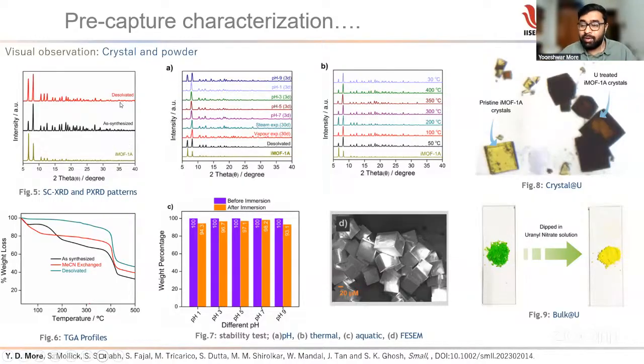So after doing the basic crystallography of the MOF, what we did, the desolvated, that is activated phase of the MOF, was treated in different acidic and alkaline medium. What we saw, we need to have a MOF at least stable till pH 5, pH 7 plus, to have the real-time application in the seawater.